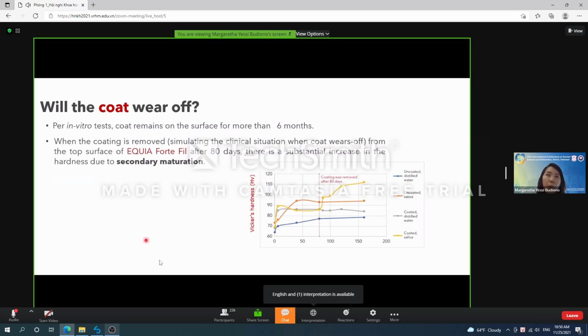Now, one of the most often asked questions is, will the coat wear off? Our study shows that the coat can remain inside the mouth for more than 6 months. But after it wears off, we don't need to reapply the coat, because by that time, when the restoration is exposed to the saliva, the restoration will undergo secondary maturation that further increases its hardness.